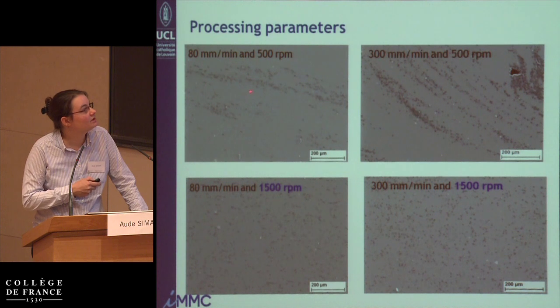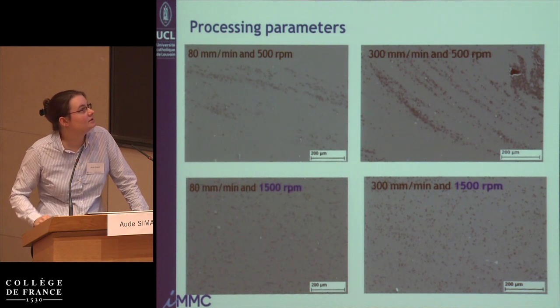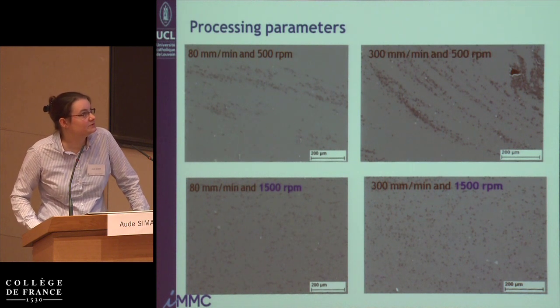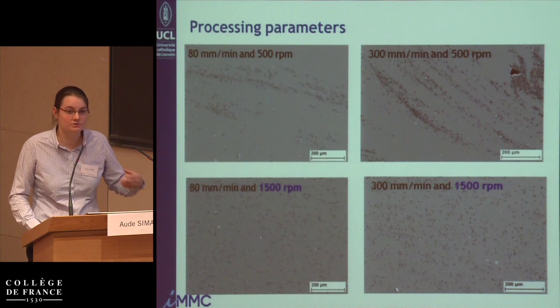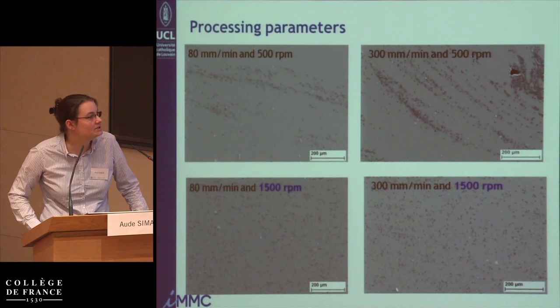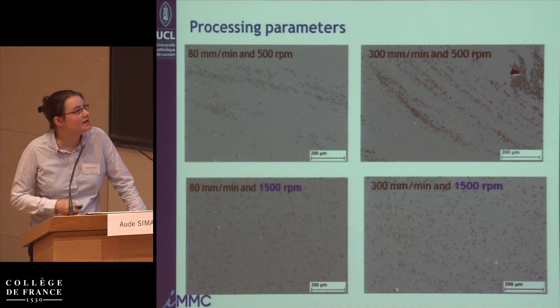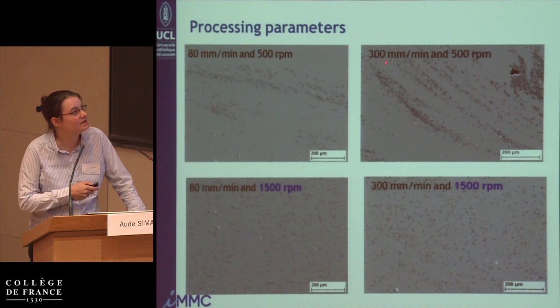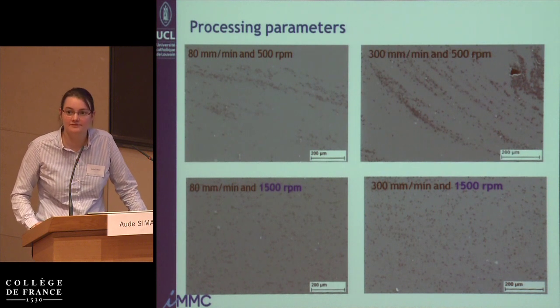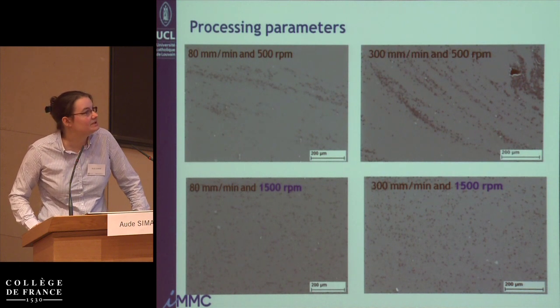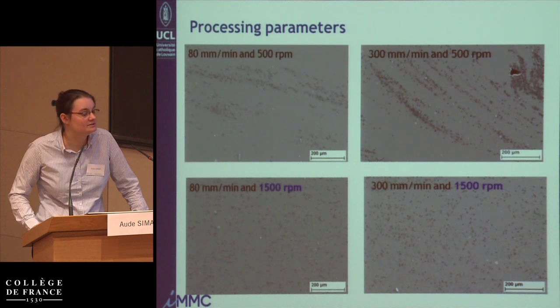If you use too low rotational speed and advancing speed, well, the distribution of fiber will be not too homogeneous. And here, with these parameters, a larger advancing speed and a lower rotational speed, you even have defects that appear, so holes in your material. That's of course not desirable.